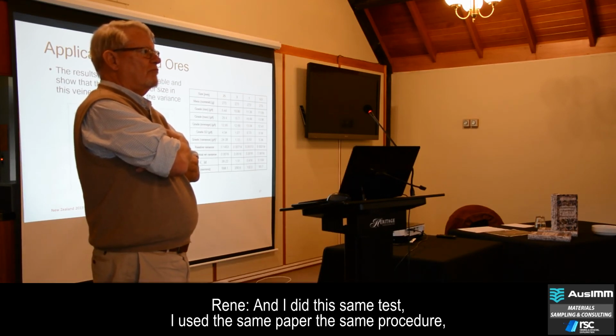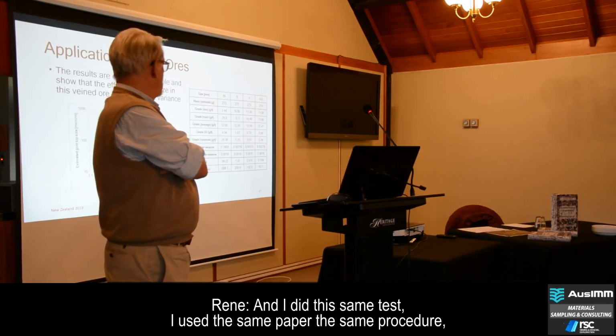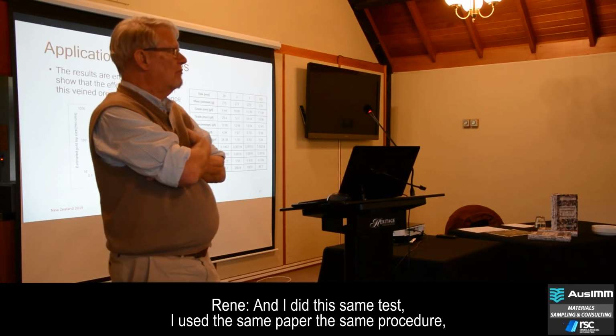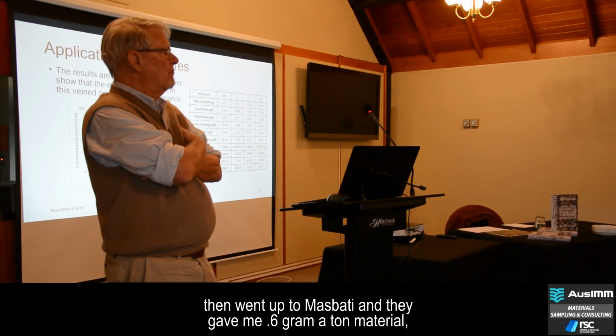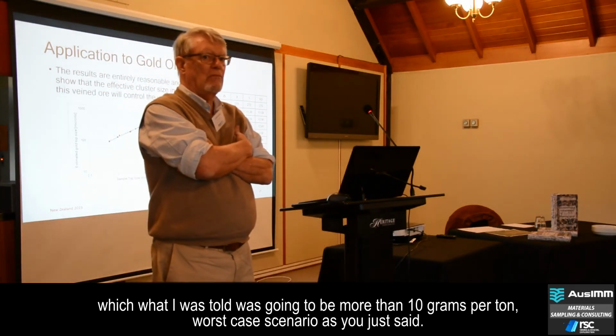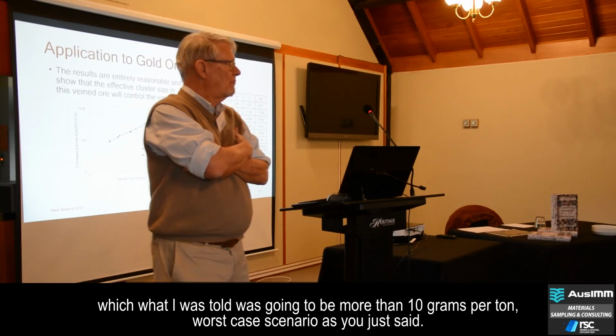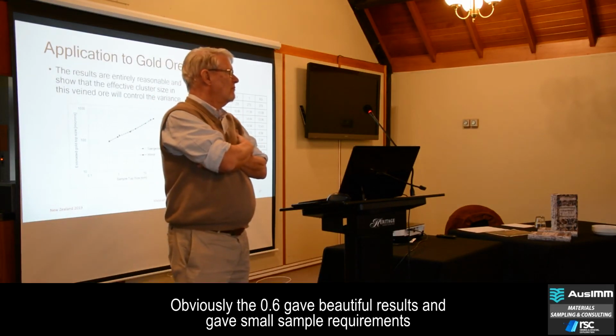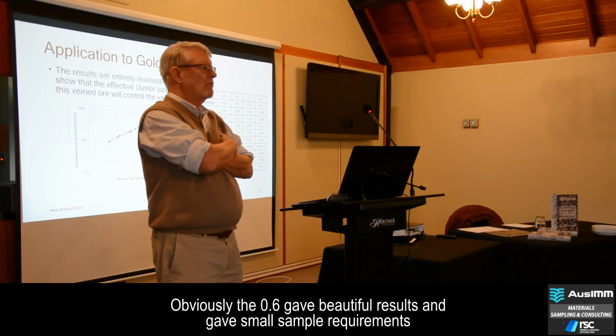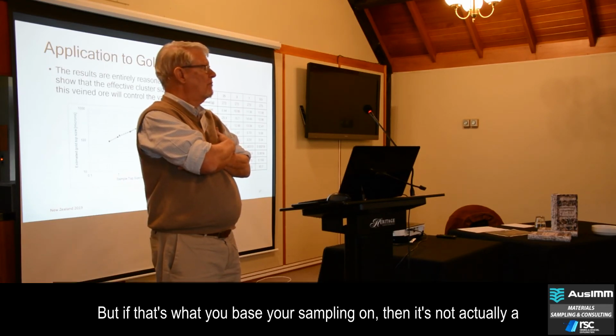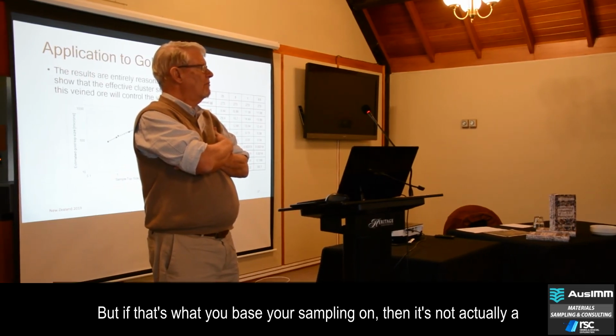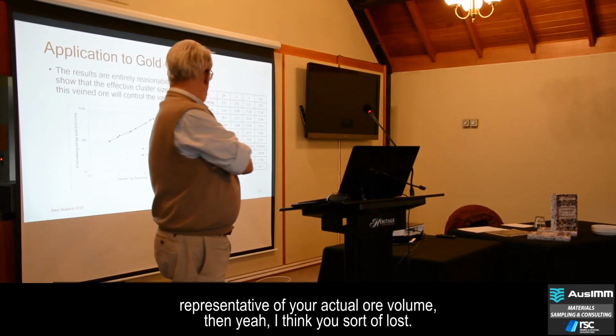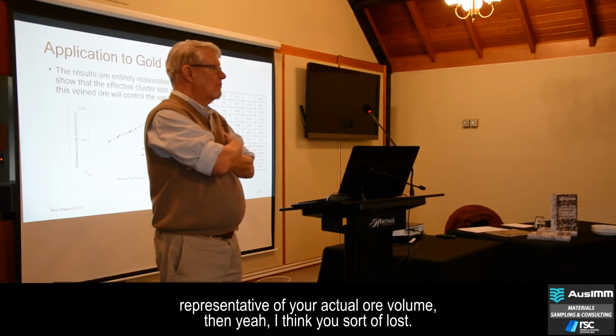Yeah. And look, I did this test. I used the same paper, the same procedure, and then went on to Masbate, and they gave me 0.6 gram per ton material, which I was told was going to be more than 10 grams per ton. Worst case scenario, as you just said. Obviously, the 0.6 gave beautiful results and gave small sample requirements, but if that's what you base your sampling on, and it's not actually representative of your actual ore body, then you're sort of lost.